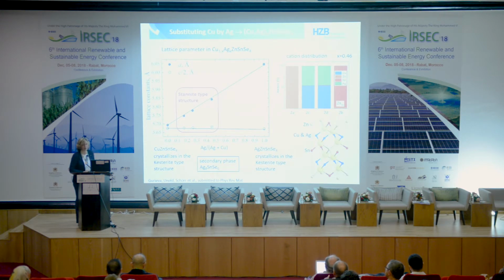Unfortunately, we form a secondary phase which has a low band gap. This is Ag8SnSe6. It has the argyrodite-type structure, and this group of materials is well known in thermoelectrics, especially with copper instead of silver.